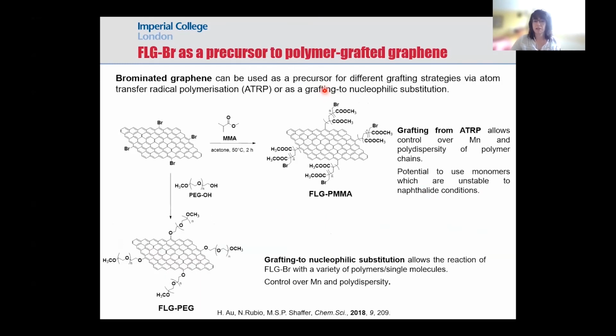So we are able to grow a polymer on the surface. In this case, we chose a methyl methacrylate, similar to before, because we wanted to see the compatibility with epoxy resins. But we can use any other monomer that can go through atom transfer radical polymerization. And also we are able to substitute these bromine functional groups with another molecule, which can be, in this case, a polyethylene glycol polymer, which can be useful for biological applications. But again, these bromines can be substituted with any other functional group of interest.